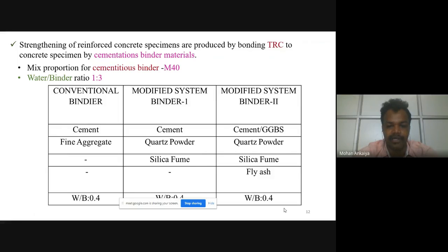For modified binder 1, in order to achieve higher strength, we implemented more silica, which is the major component for the increment of calcium silicate hydrate content in the concrete. To implement more strength, we replaced cement with quartz powder and silica fume. Similarly for modified binder 2, cement 50%, GGBS 50%, plus quartz powder, silica fume and fly ash.